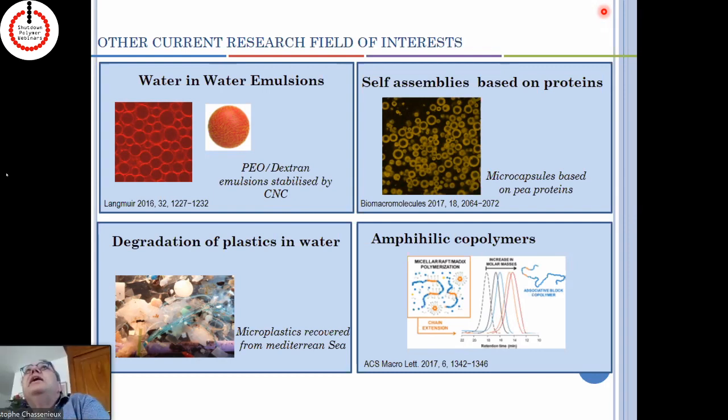All the light scattering results that have been obtained in order to derive the aggregation number were obtained in the dilute state, in order to ensure that we measure a true molecular weight and not an apparent molecular weight. So all the results that I've shown on aggregation number as a function of the composition of the mixture were obtained in the dilute state. Only rheology has been done at pretty high polymer concentration, and not that high, because the percolation concentration of the system can be of the order of 10 grams per liter. So it's not that concentrated.